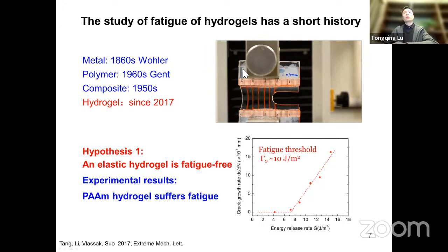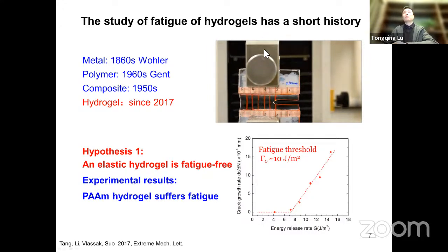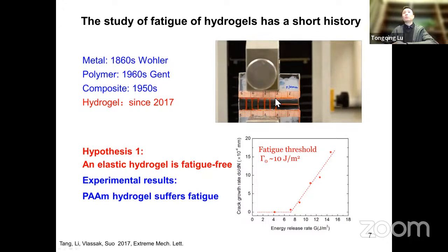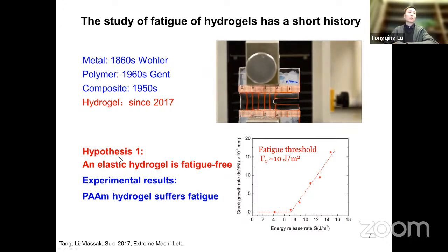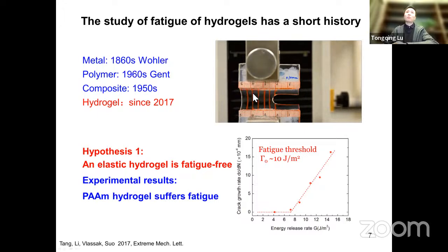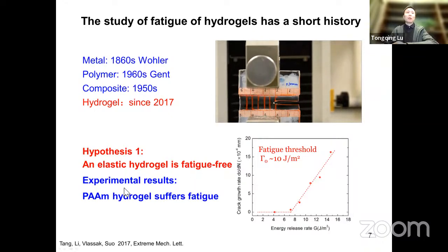So the method is similar. Just apply a cyclic load and record the crack growth. So in this original paper, they have the first hypothesis, because the hydrogel they test is a very purely elastic material. So their hypothesis is that this material may be fatigue-free. Okay, but their experimental result is that this hydrogel also suffers fatigue.